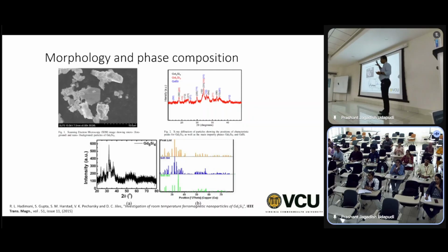At high temperature, it's monoclinic, and 5,4 is orthorhombic, and when it's orthorhombic, you have lots of planes, so you get these really complex peaks, and it also has small phase of 5,3, small phase of 1,1. So this is what we want. That is the major phase, but there is some impurity here. Okay, so those peaks we can see. The red is 5,3, the blue is 1,1.